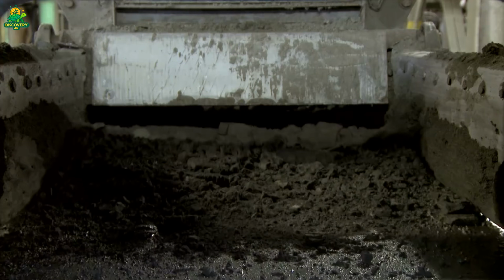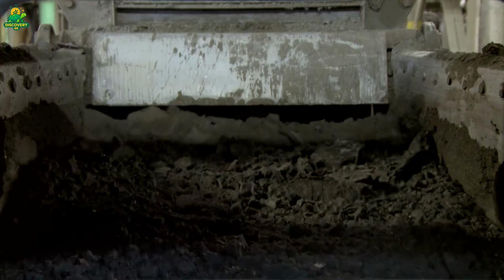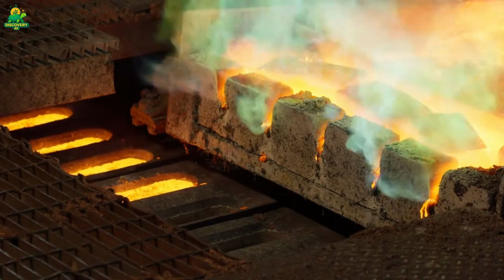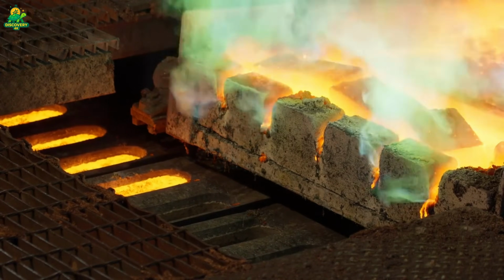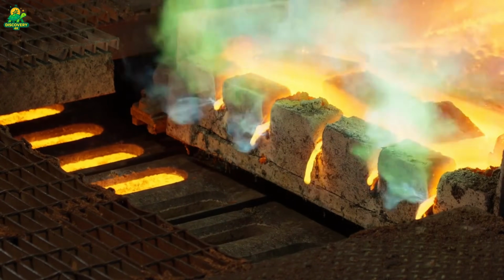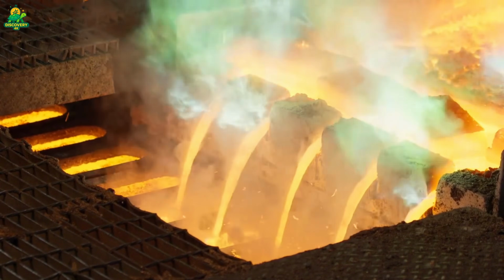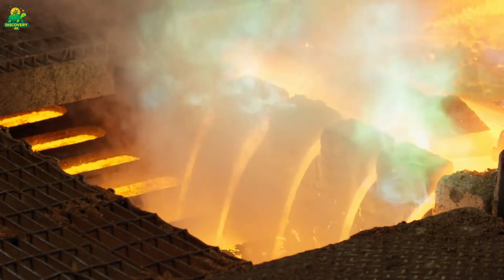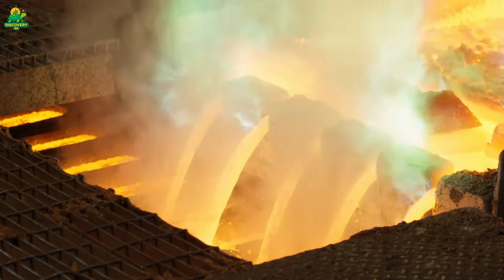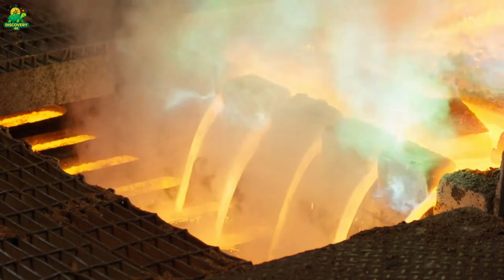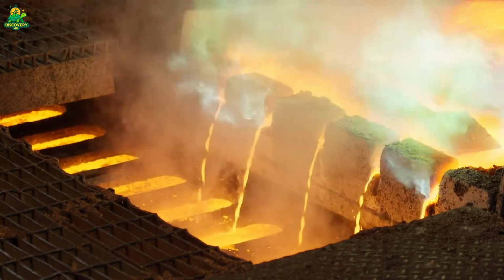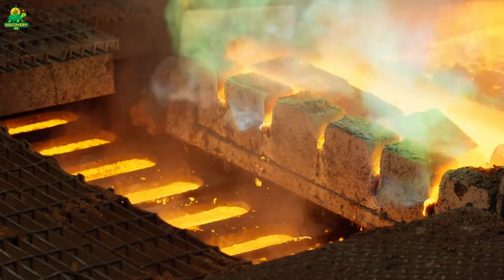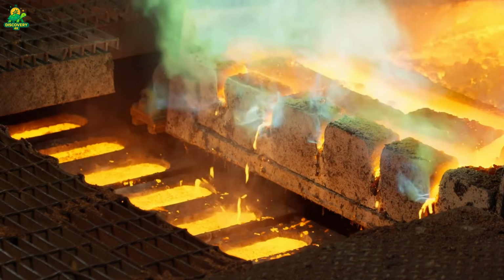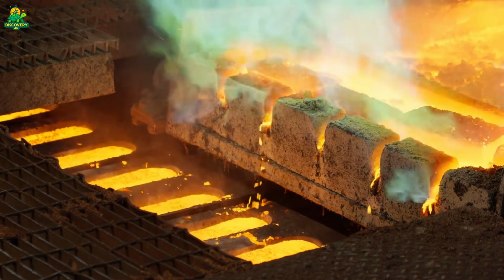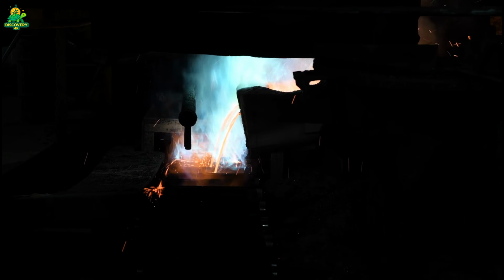But for modern applications, that's not enough. To achieve the required purity, copper undergoes electrolytic refining. Large sheets of copper are placed into tanks filled with electrolyte solution. An electric current passes through the system, causing pure copper to deposit onto cathodes while impurities fall away. After this process, the copper reaches a purity of 99.99%. One of the highest levels of purity achieved in industrial materials.